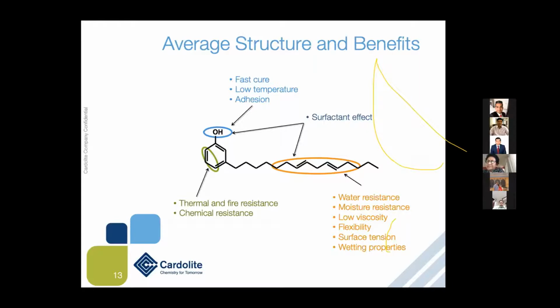Now, this is the base molecule of CNSL. If you look on the top, it has an open OH group, which gives you fast cure, low temperature cure, as well as excellent adhesion. You have the phenolic ring. The phenolic ring gives you high thermal resistance, fire resistance, as well as chemical resistance. And we have the long chain, which gives excellent water resistance, moisture resistance, that is hydrophobicity, flexibility, good surface tension, and water wetting properties. That is why we spoke about the surfactants. It gives a natural surfactant effect.